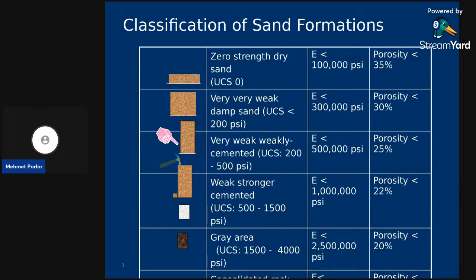The next one in line is very, very weak damp sand. That's wet sand. UCS can be less than 200 psi, and Young's modulus less than 300,000 psi, and so on. Without going through all of them, if you get into the UCS range of 1500 to 4000 psi, with Young's modulus of 2.5 million psi, you get into a gray area. All the other ones up there require some sort of sand control, and this is now a gray area, meaning you may be able to get away with no sand control.